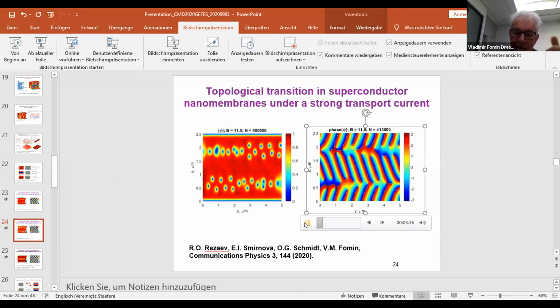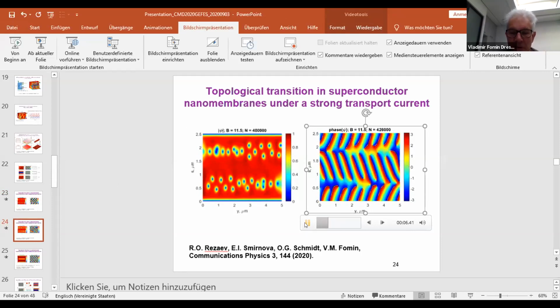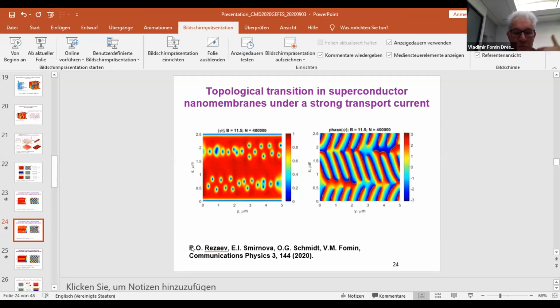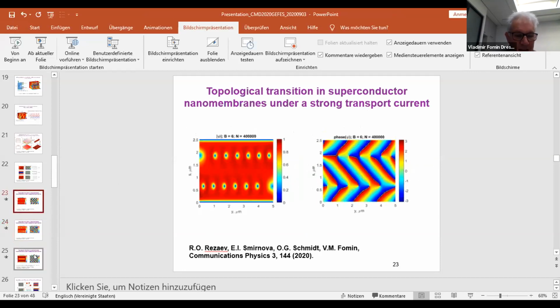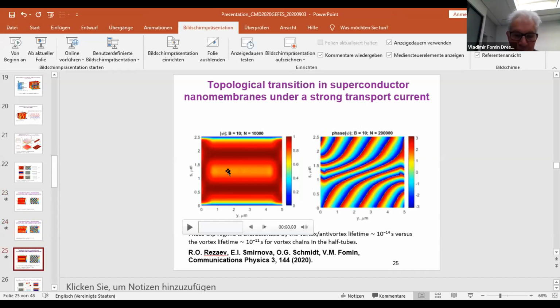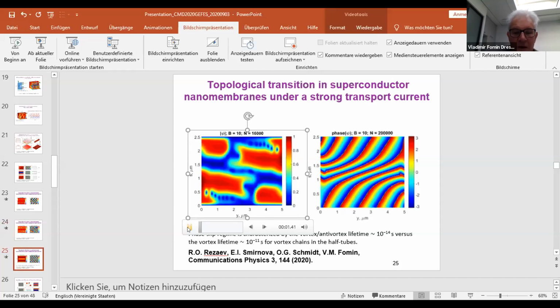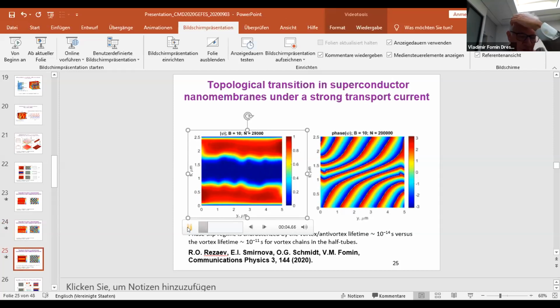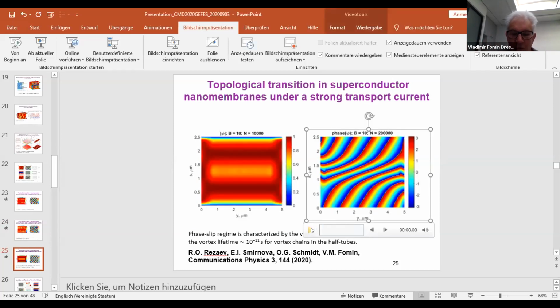We can estimate the winding number for every defect. But interestingly, a transition between a regime of one chain to two chains is absolutely different. This is magnetic field 10 millitesla. If we wait till the transition from the initial state finishes, we see here a picture which practically does not change. It resembles a phase slip in the center. But what is behind this phase slip? And now wait a little bit.